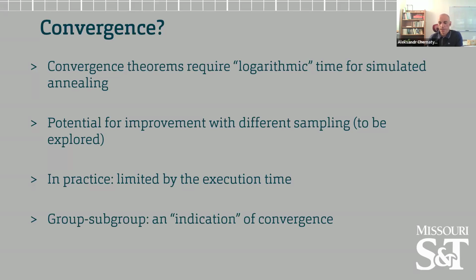One other thing which is useful in this context is if I manage to find a lowest energy state in a particular group, then I should be able to find the same lowest energy state in every subgroup of that group. There are, of course, 230 space groups available, and many of them are subgroups of each other. If I find the same structure as the lowest energy structure in every subgroup of a given group, then that gives me some degree of confidence that this is the lowest energy structure. It's only an indication, an additional piece of evidence that we can use, but nevertheless, we want to take advantage of that.